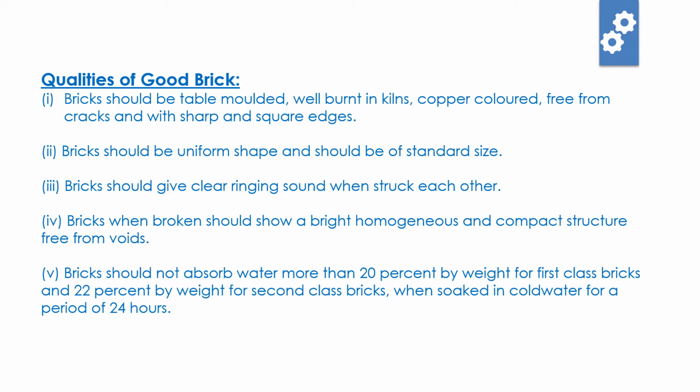Bricks should not absorb water more than 20% by weight for first class bricks and 22% by weight for second class bricks when soaked in cold water for a period of 24 hours.